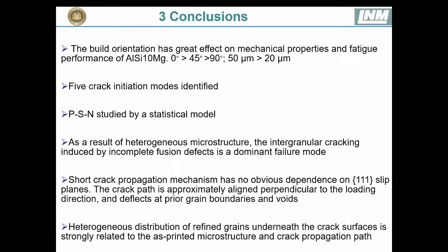conclusions are drawn. So firstly, the build orientation has a great effect on the mechanical property and fatigue property of these additive manufacturing alloys, and the horizontally manufactured specimen has a higher strength than the 90-degree manufactured specimen, and 50 microns printing powder size leads to a higher fatigue strength than that of 20 microns. And 5 different kinds of crack initiation modes are identified, and the statistical model is used to perform the P-S-N study. And as a result of heterogeneous microstructure, the intergranular cracking induced by incomplete fusion defects is a dominant failure mode.